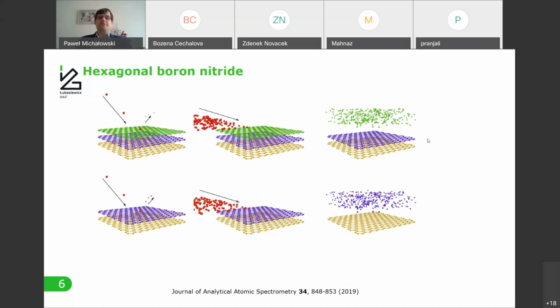And I will start with the very first example of such an application of a dedicated procedure. This is one of my very first major achievements in SIMS, which I consider to be very, very good: the analysis of the hexagonal boron nitride. So my idea was to actually reach the atomic depth resolution in this experiment. And I did it for the first time. I used a very low impact energy and low density beam to probe just the top layer of hexagonal boron nitride. So I obtained some information from there.